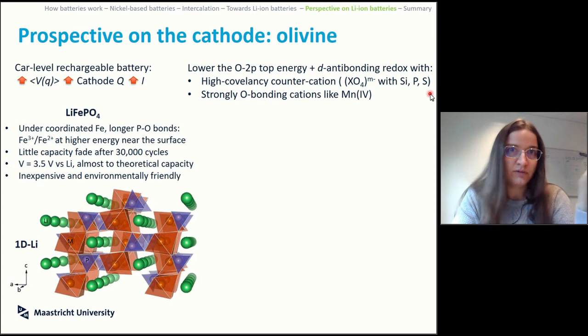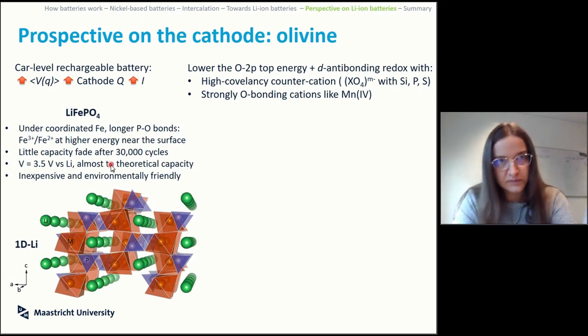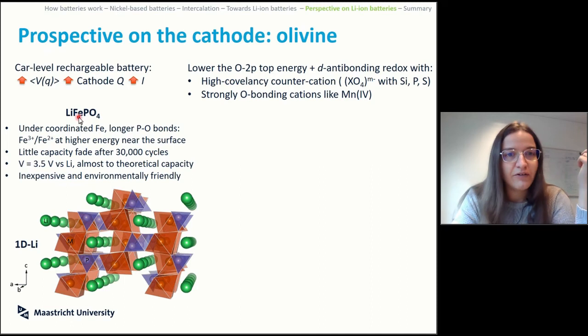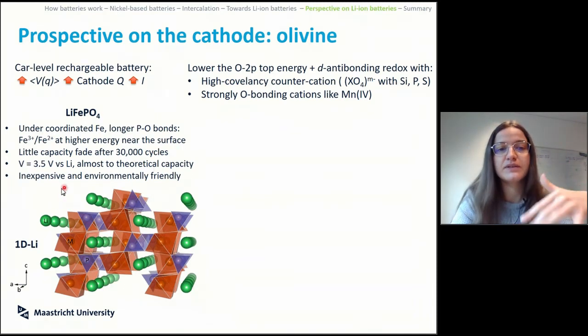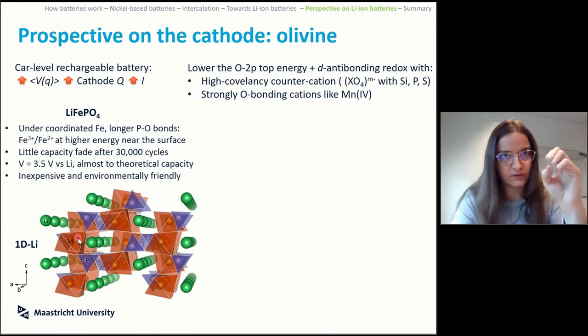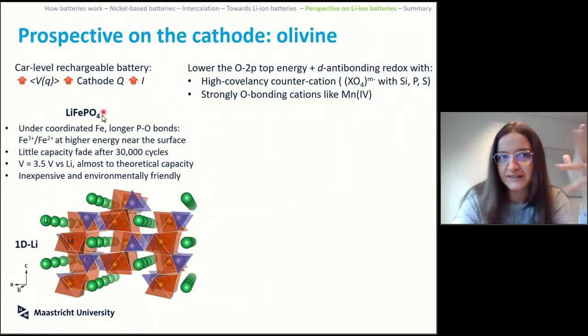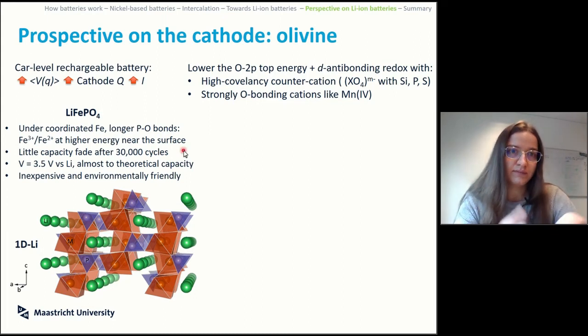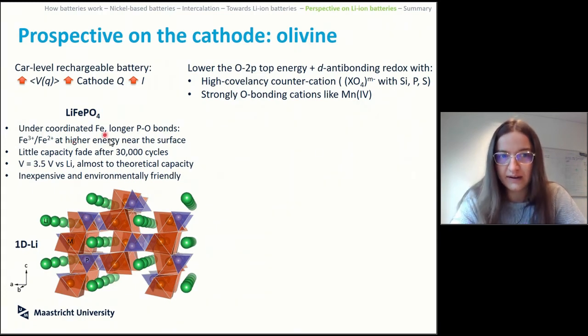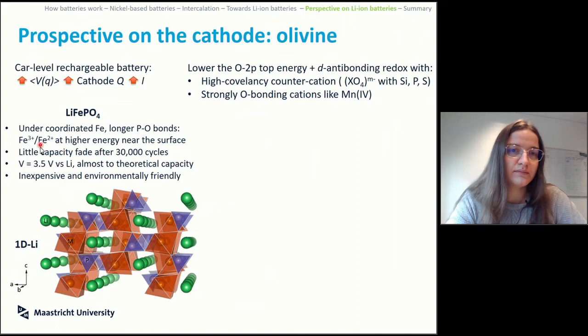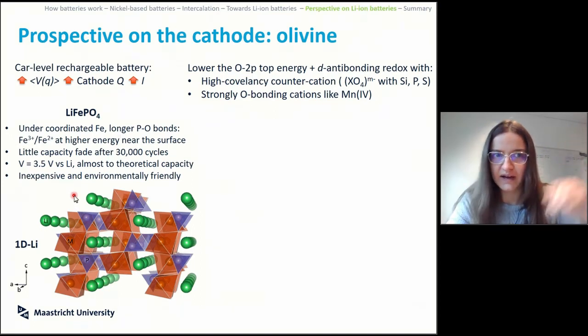So this thing, can it be done? It can be done. It can be done in structures that are not the spinel and not the O3 layered structure that we saw before. Something like lithium iron phosphate, right? This thing becomes an olivine. So the bond of the oxygen with the counter cation in this case is much stronger. In this case, iron is under-coordinated, so it has a lower coordination in comparison to what it could potentially do. And you have the redox couple of iron 3, iron 2, which goes a bit higher.